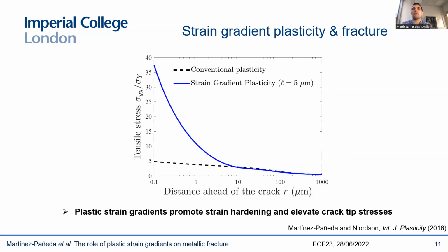So the implications from a fracture mechanics point of view is that if you're dealing with a fracture phenomenon where the critical distance for fracture, the fracture process zone, is very large, like for example, ductile fracture, then you don't really care that much about these GND effects, about these plastic strain gradients, because essentially you are hundreds of microns away from your crack tip.